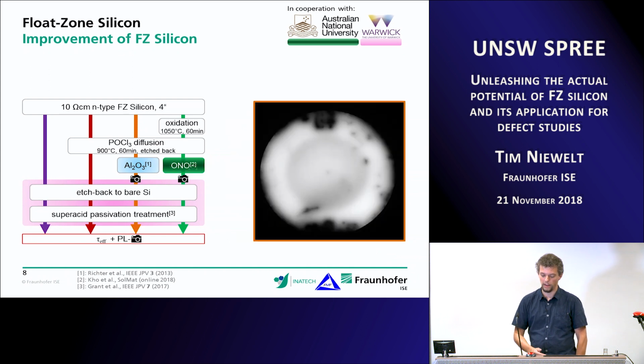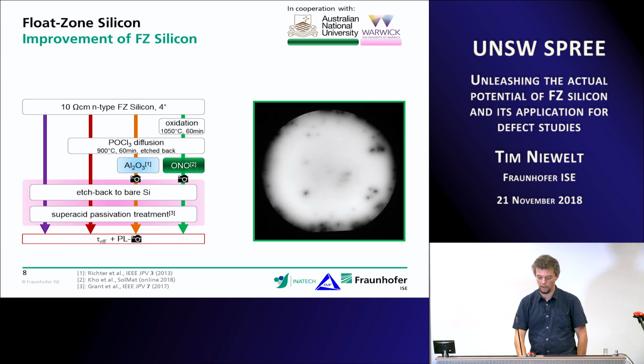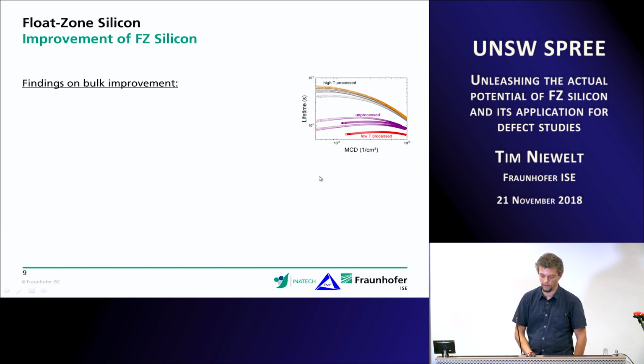Here, for example, is a PL image of one of these samples that just underwent a POCl3 diffusion. As you see, this bad region in the center is not as bad as it was before when compared to the rim, but it's still visible, so there is still something limiting our lifetime. And after the oxidation treatment, we see that this is pretty much improved, and the slightly lower lifetime in the center region is quite likely due to these handling artifacts, or handling damages.